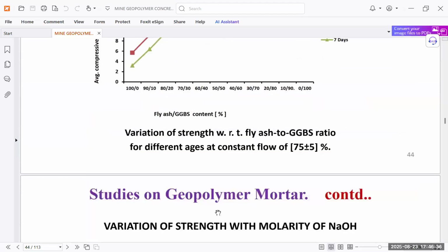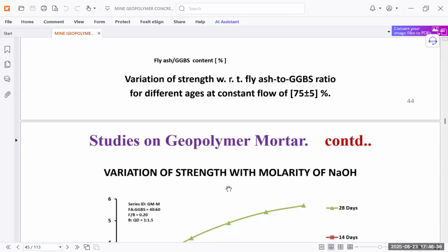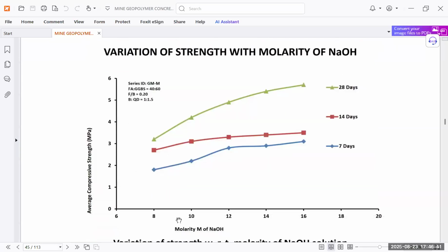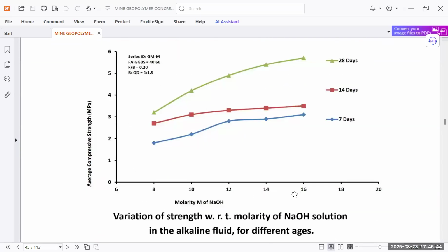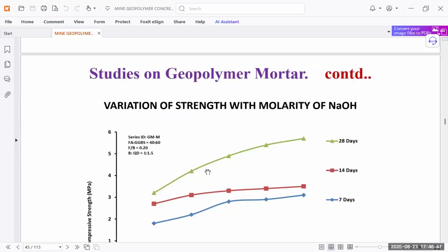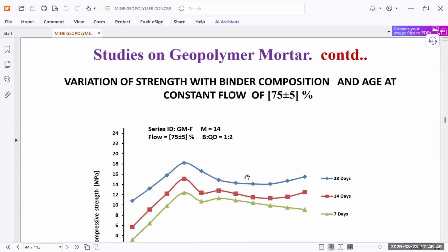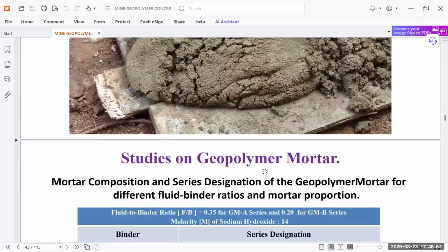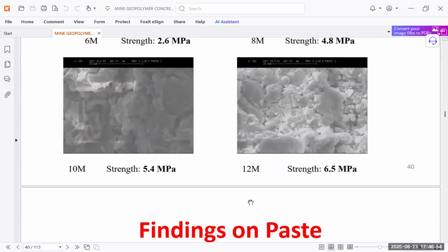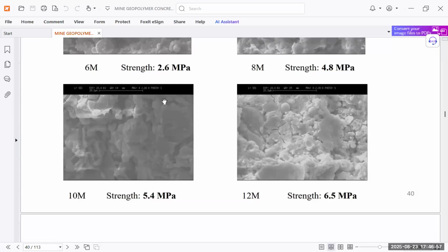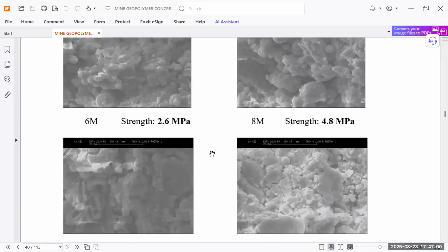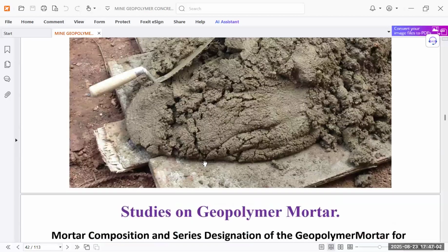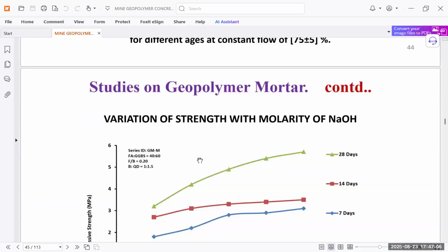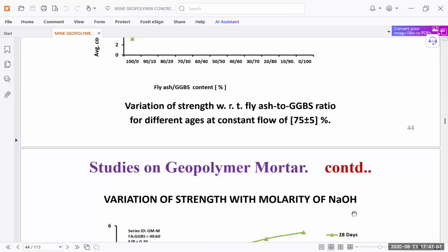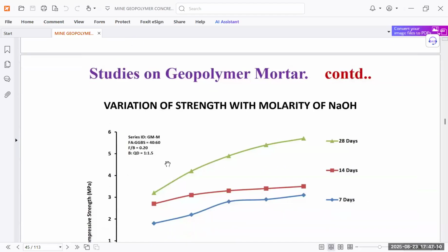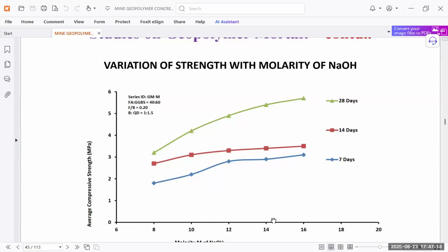Further graphs were plotted for the variation of strength with molarity of NaOH. Now the molarity is changed. We have plotted for different molarities: 6, 8, 10, 12, 14, 16, 18, 20. And we can get this variation of strength with molarity. As we already discussed in the previous case, changing the molarity gives different strength, with 12 molarity, 10 molarity, 8 molarity and 6 molarity shown here. In the same way we plotted this graph of NaOH molarity for 28 days, 14 days and 7 days. For different molarities, we have obtained this graph.